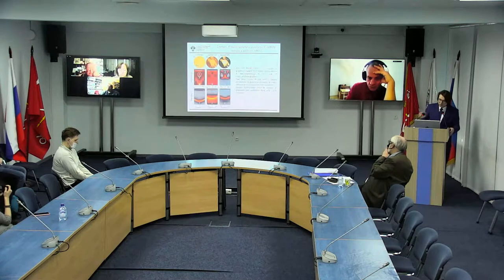And the major conclusion that we can make is that monocrystalline graphene on cobalt and nickel is not prone to this oxygen impact, and its initial state is easy to restore, whereas polycrystalline graphene at room temperature during this contact with air is partially intercalated with oxygen, and we see the emergence of the C1 component. You see it in green. And further heating in ultra-high vacuum aggravates the situation, and more than half of graphene is intercalated by oxygen, and it shifts to free condition.